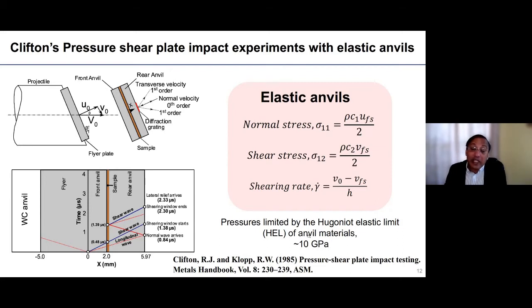But one of the challenges in this technique is that if we want to use the elastic characteristic analysis, then this is limited by the Hugoniot elastic limit of the anvil materials. So even the best of the materials, things like tungsten carbide, this is limited to approximately 10 gigapascals or so. The Hugoniot elastic limit limits the regime in which this elastic characteristic analysis can be used. So the work I'm going to describe essentially extends this technique beyond the Hugoniot elastic limit.